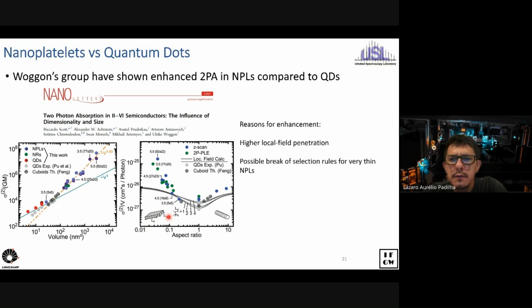And another reason they would speculate, and this has not been proven yet, is that, for example, for nanoplatelets, you would have different selection rules, and the breaking of the selection rules that you would have in quantum dots, in this platelet type of nanomaterial, would allow other transitions that were not allowed before, increasing the density of final states and finally increasing the two-photon absorption cross-section.